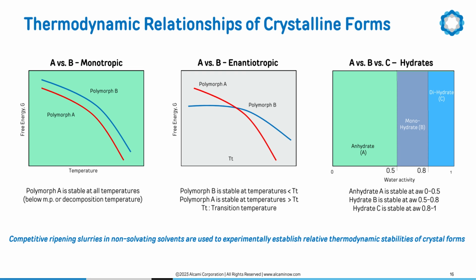This is to ensure that they operate within the ranges that overlap with the stability region of a target polymorph. For instance, in the anhydrate, monohydrate, dihydrate system that is shown to the right-hand side, if the anhydrate is desired, it needs to be crystallized or formulated in solvents at water activity below 0.5. And it also needs to be stored at low humidity conditions in order to avoid conversion to the hydrates.